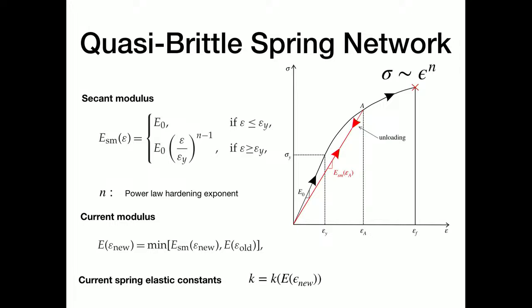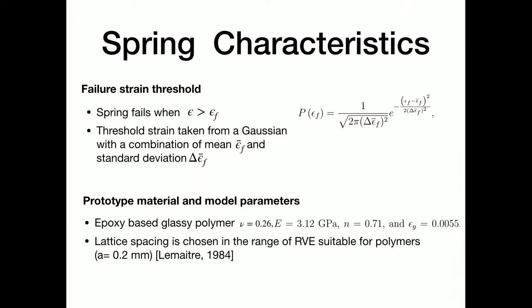We assume quasi-brittle behavior, which means that at any point, if you are unloading, the elastic behavior is such that you reach zero load at zero deformation. And then we put some rules for that so that it happens. And spring behavior now we take from a normal distribution, and the disorder is controlled by taking the different values of this multiplicative factor, which is the standard deviation is the multiplicative factor times the mean failure threshold strain. We use a prototype material, which is an epoxy-based glassy polymer. These are the properties we determine from experiments and choose a lattice spacing appropriate for polymers.